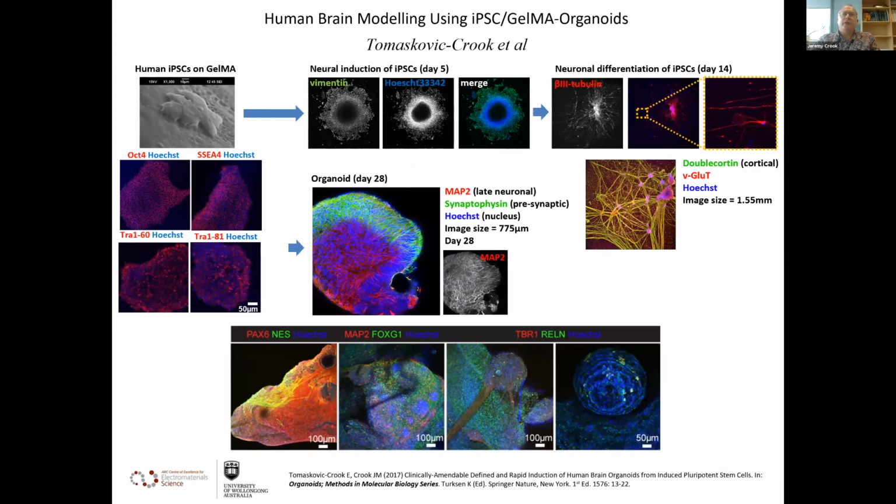In order to circumvent the shortfalls of conventional methods to generating cerebral or brain organoids, we've replaced standard mouse sarcoma, that is tumour-derived Matrigel growth substrate, with more defined and clinically amenable gelatin methacrylate, commonly referred to as GelMA. GelMA is a versatile semi-synthetic matrix that incorporates the intrinsic bioactivity of natural matrices with the fidelity of synthetic biomaterials.